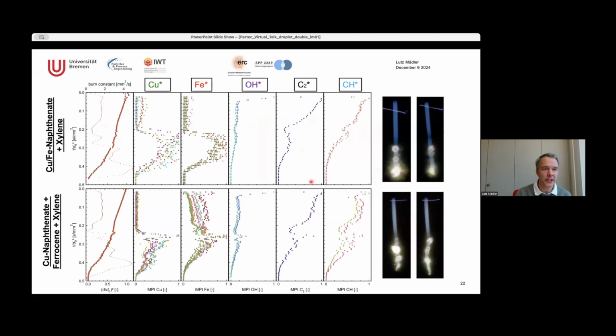So basically, to make that story, we have these two different precursor solutions. And in this one here, copper and iron come out at the same time. And at that moment, that is the droplet diameter. And the deviation of the droplet diameter is the burning constant. At that moment, the burning constant goes down because evaporation basically stopped. Then we have the explosion and everything comes out. While in the other case, the iron comes out first and the copper later. And you also see a difference in this burning constant, although you have another explosion here for the copper.